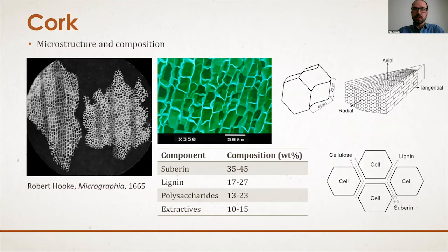Suberin is important in the properties of cork because it's a lipophilic biopolymer and is responsible for its elasticity and compressibility. And basically its viscoelastic behavior and relaxation properties, as well as the impermeability and also the resilience of this material. And of course, the other constituents are also important. For instance, the lignin gives the structural stiffness to the cell walls.